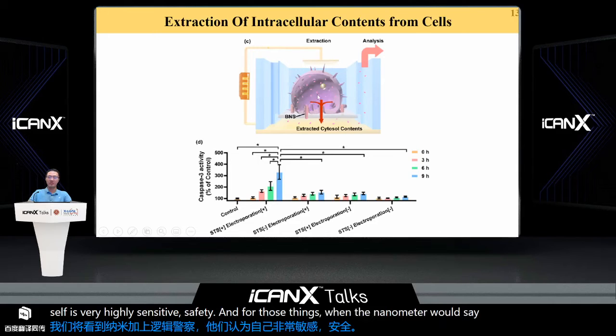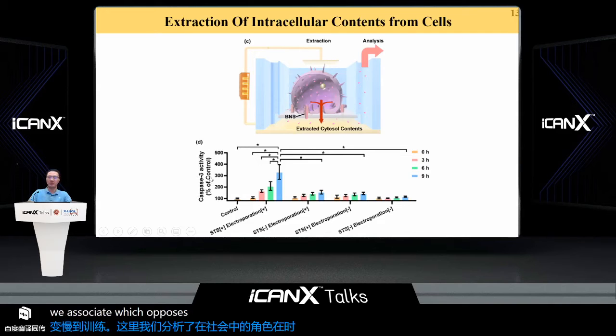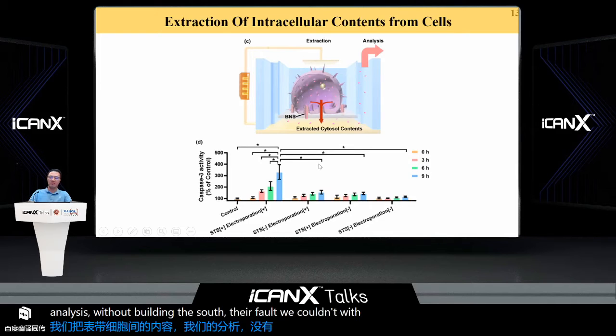And for the sensing, when the nanoneedle penetrates the cell membrane, the cytosol could be diffused through the nanochannel to the external channel. Here we analyze a typical intracellular enzyme, caspase 3, which is associated with the apoptosis activity of the cell. We could extract the intracellular contents every 3 hours for analysis without killing the cell. Therefore, we could detect the dynamic change of caspase 3 in exactly the same set of cells.